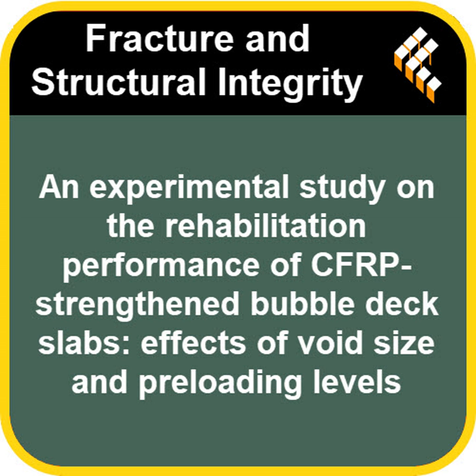Exactly. And the unreinforced 60-millimeter void slab, the SB60, fared a bit worse. It showed a more significant 13.5% reduction in ultimate load capacity. Okay, that's a bigger drop. And a 2.3% increase in deflection compared to the solid slab. Still sagged more, but the load capacity drop was the bigger story there. So what does this all mean? It's clear that the very presence of these voids inherently reduces a slab's ability to carry the maximum load, and it can increase how much it sags under load. And importantly, the bigger the void, the greater the reduction in performance, particularly load capacity. It's a direct consequence of having less concrete.